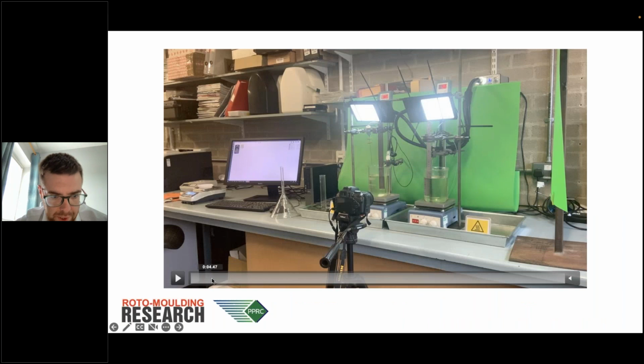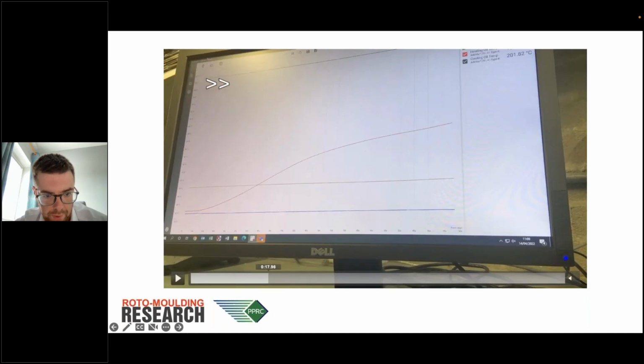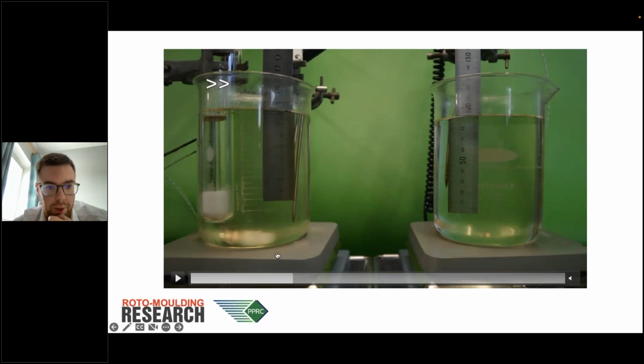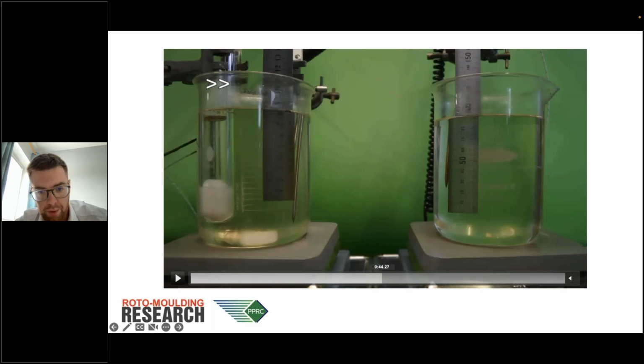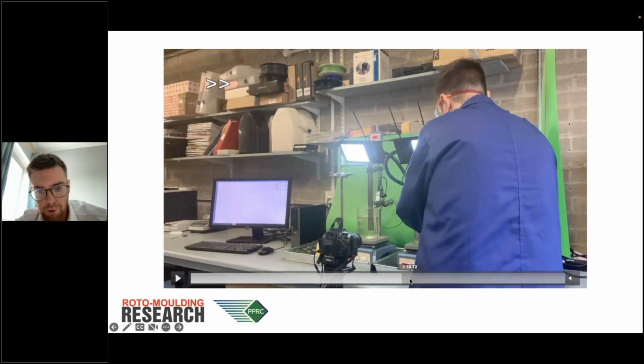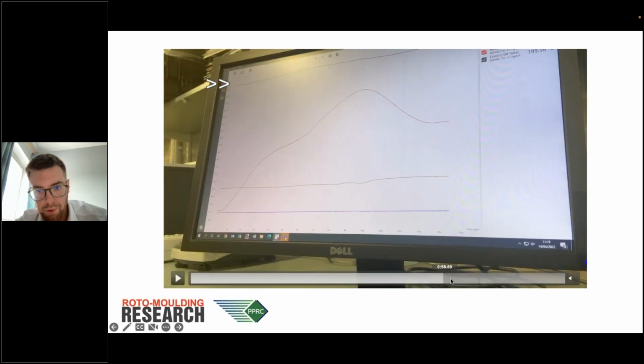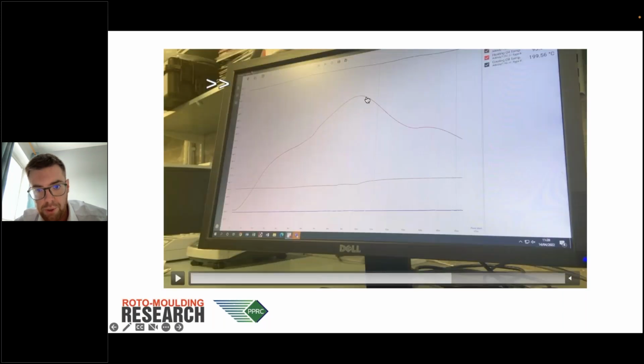So just briefly, because this video isn't going to show very well, what I have is 2 oil baths. One is providing the heating, and one is providing a controlled cooling rate. And what happens during this is, so this is the view that the camera sees. The test tube's lowered into the heating side, and over a period of time, the polymer starts to compact as it melts, and then eventually starts to expand as the blowing agent activates. In this image here, that then gets moved across to the right-hand side, and you can see the temperature reduction of the melt in that image on this side of the trace.